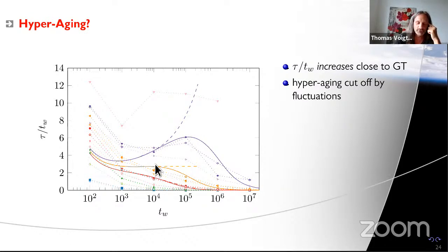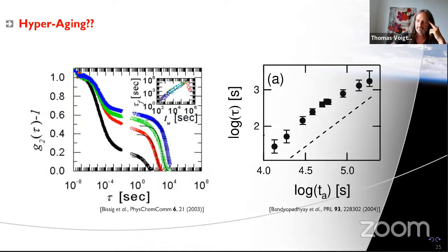And for comparison, as solid lines, I plot the predictions of the non-equilibrium version, Magdalena's theory combined with Tommaso's and mine. So we're really putting everything together here. And you see this matches quite well. So I would say this is something that needs to be explored more. There might be arguments against hyperaging. You might find it strange that the system has a relaxation time that grows faster than you can actually ever wait.